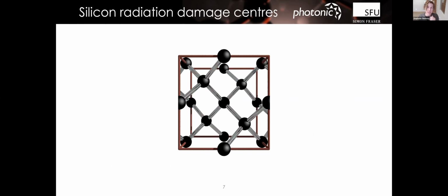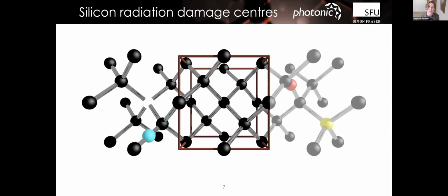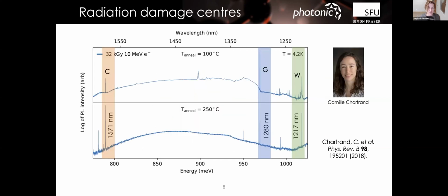So really these damage centers is what you would characterize them as, and what they would do is they would damage silicon and see what kind of luminescence features would crop up. And these are all kinds of structures. They're native to silicon, whereas erbium you could kind of put into anything. As native to silicon, these kinds of structures, we began to take a look. So the first set we looked at a couple of years ago now resulted in the kind of centers that could be readily created with the natural impurities within our silicon-28 ensembles.